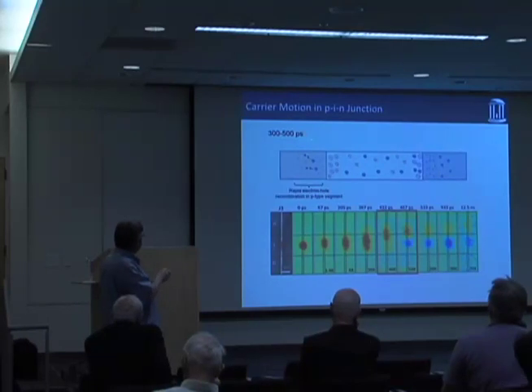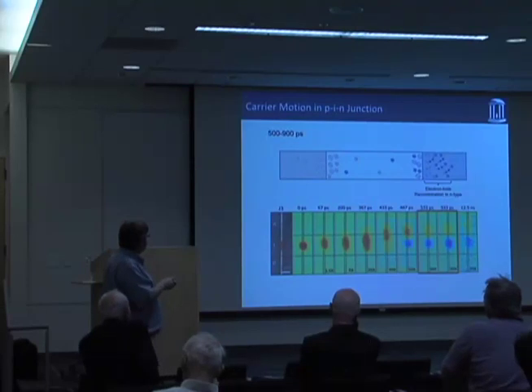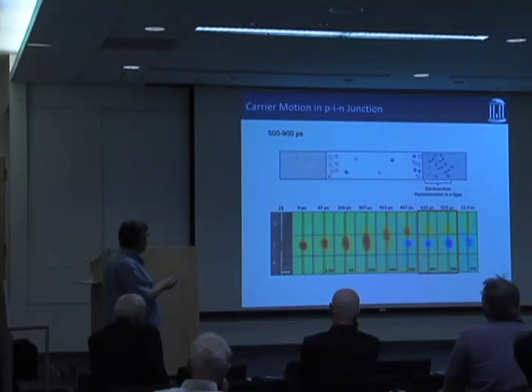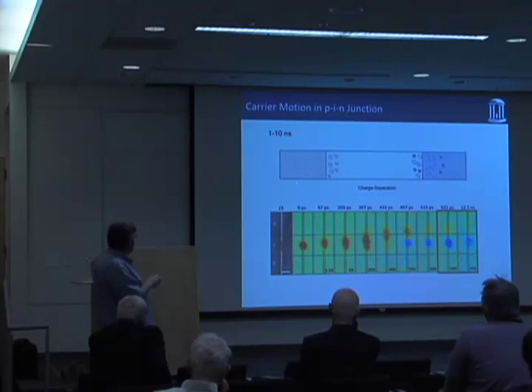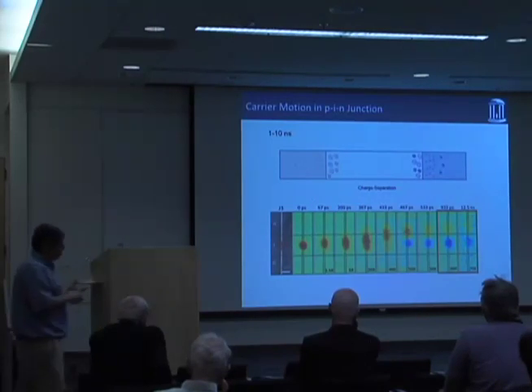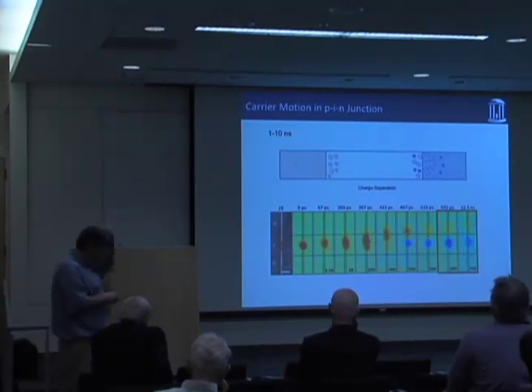In the p-type region you get very rapid recombination, so that signal all goes away. And then between 500 and 900 picoseconds you observe the recombination in the n-type region, and then at really long times you have this charge separated state. We don't see the signal from the holes, and that's kind of interesting.